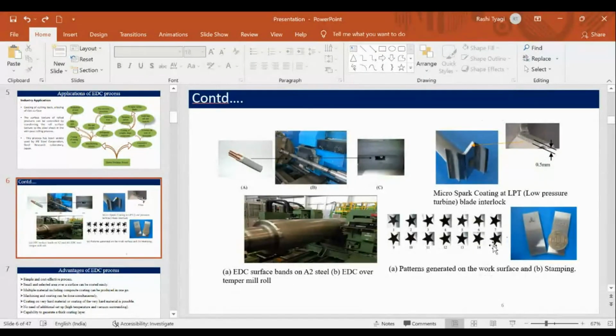So this is a pattern generated on the work surface, a stamping. The patterns are generated by using different parameters in the EDC process. Different parameters mean different currents, different voltages, or different process parameters that we are utilizing. So how can these patterns be generated? I have told you that a complex shape workpiece can be used. If we are using any shape in the compact tool, then we can deposit the stamp of the shape. So a reverse pattern will be generated, not a cavity but in coating form. So there are two stamps made by using the EDC process, in which you can see two company stamps performed by using electrical discharge coating.